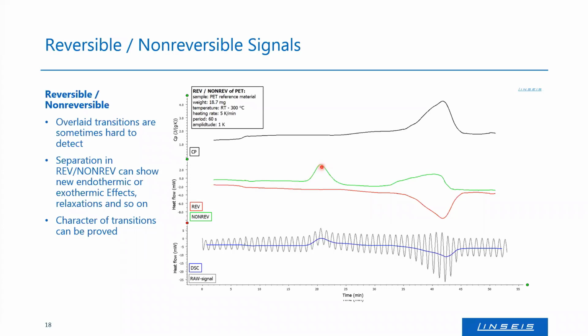What else we can see here is the recrystallization, clearly. And what's interesting here, we can't see this in our DSC measurement itself. There is a second recrystallization near to the melting or in the melting, when all the remaining amorphous parts are getting crystalline before they melt. And now it's also possible to evaluate this. The reversing part is basically the same as the CP. You can see here the Tg and also, of course, the melting. So this peak is the main advantage, and of course also the hysteresis peak or the relaxation, because you can't find or evaluate them in the blue curve here, so in the raw or conventional DSC signal.